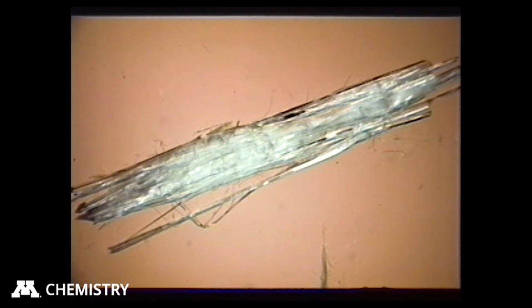But the problem is, when you put this crystal in the X-ray beam, it does this. This is not a phase change, it's not a polymorphic rearrangement, it's not a desolvation, it's not a hydration. This is exactly the same compound as we had before. We don't know why it does it, and we don't know how X-rays can cause this to happen, but it mechanically just shatters to pieces. And there's no phase change. Every chemical and physical property you'd measure on it would be identical. The only thing that's different is that it is shattered into these little pieces. Interestingly, many compounds in the tri-keto series have this property. Many of their crystal structures have this property, which we also don't understand.